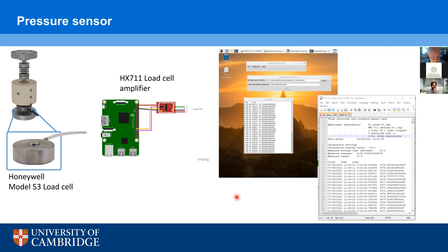In terms of calibrating the pressure sensor via the load cell amplifier, we had a series of different weights, so 0 grams, 50 grams, 100 grams, and 200 grams, and looked at the linear increase in the output voltage compared to the load that was being applied, and used this to calibrate the load sensor. And then before each experiment, we take an average of the output of the load sensor and use that as a baseline.